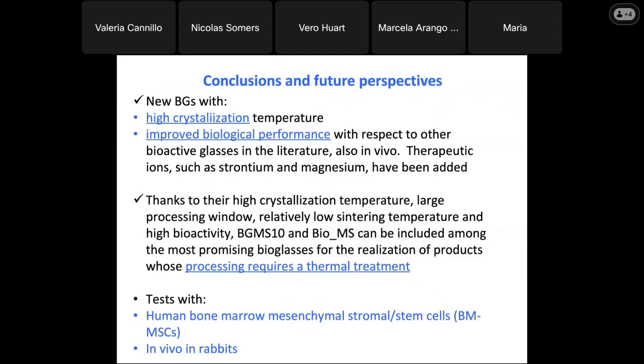So, concluding, these novel bioactive glasses were characterized by a very high crystallization temperature and at the same time improved biological performance with respect to other bioactive glasses in the literature, also in vivo. And this was due to the addition of therapeutic ions such as strontium and magnesium and other ions. And thanks to the very high crystallization temperature, a large processing window was obtained with a very high crystallization peak temperature.